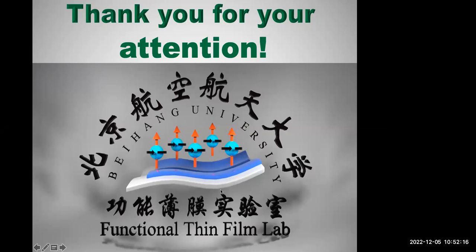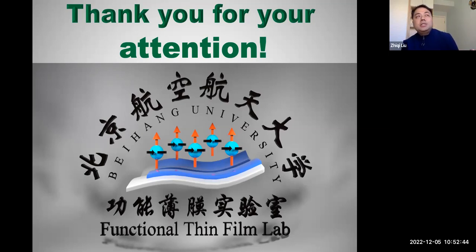Hello? Yeah. I have a question. For the piezoelectric oxide, how much strain can they apply? Because the film is on top of the piezoelectric oxide, is it the same strain that the film feels as the piezoelectric oxide applies? Okay. So the first question is how much the piezoelectric strain is. It's around 0.1%. It's very small. It's only 0.1% in-plane biaxial. It's a biaxial compressive strain mostly. Of course, for some materials you could get tensile strain, but mostly we utilize compressive strain in-plane biaxial.